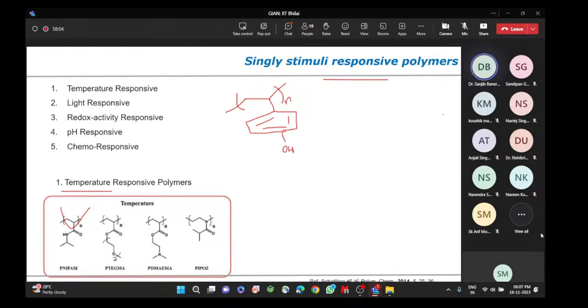This polymer exhibits UCST. At ambient temperature, this polymer is insoluble in water. When you increase the temperature to around 60 to 63 degrees, this polymer becomes soluble in water because hydrogen bonding interactions supersede the pi-pi stacking interaction between multiple aromatic rings of the pendant moiety. This part is the pendant moiety, and there are other chains that also have a pendant moiety. Just for simplicity, I took an example of phenol, but basically we are talking about polymers. Is it clear now, Navtej? Yes, sir, this is clear.